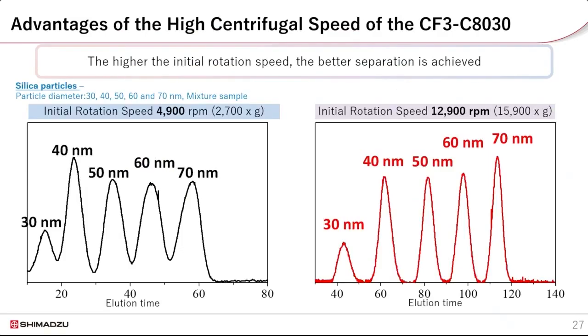I just want to show some data to explain how the higher centrifugal speeds result in a higher resolution. The study here uses silica nanoparticles ranging from 30 to 70 nanometers in size. The figure on the left are results obtained running the Shimadzu instrument at a lower speed, that is 4,900 RPM, and the figure on the right is using the same sample but acquired using the highest RPM on the Shimadzu system, that is 12,900 RPM.